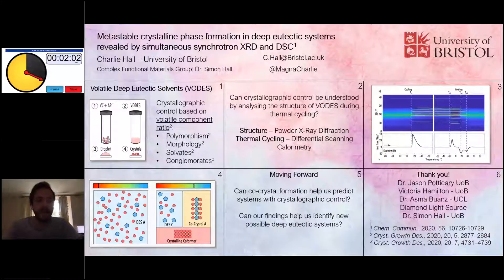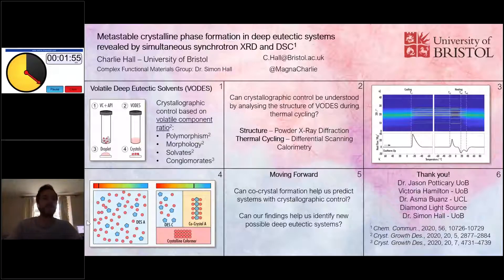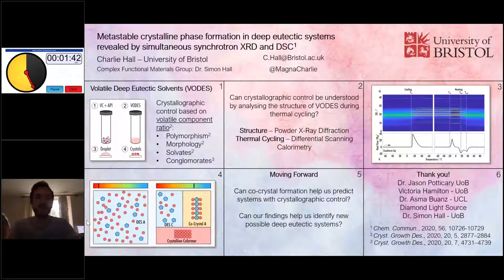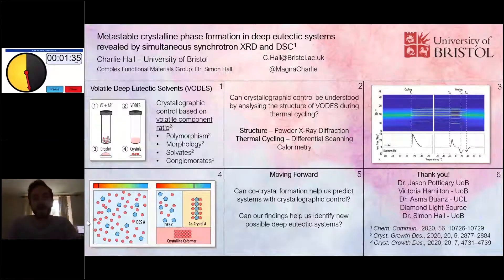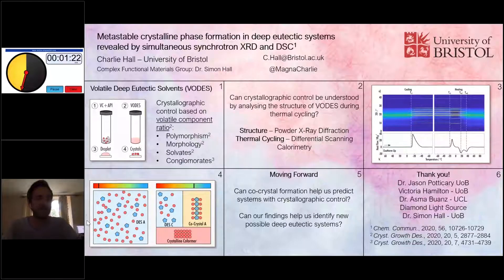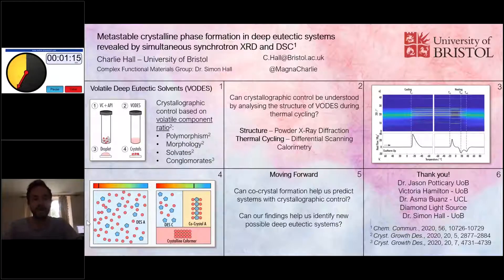The next step is looking at the fundamentals of what's really going on in these systems. I was fortunate enough to do experiments at the Diamond Synchrotron using concurrent techniques of powder X-ray diffraction and DSC — differential scanning calorimetry. In pane three, I've shown an image of some of the data we get from this. We get data as we cool down our volatile deep eutectic solvent, giving us both structural information from powder X-ray diffraction and thermodynamic information from DSC.